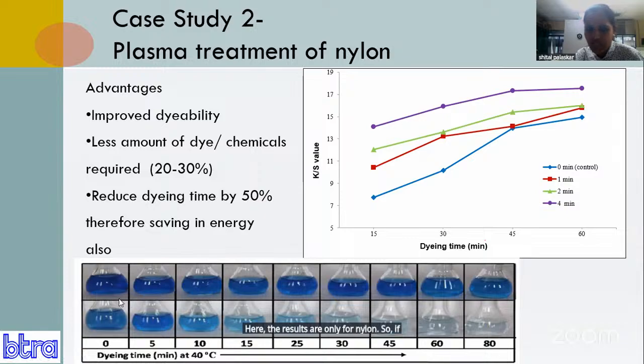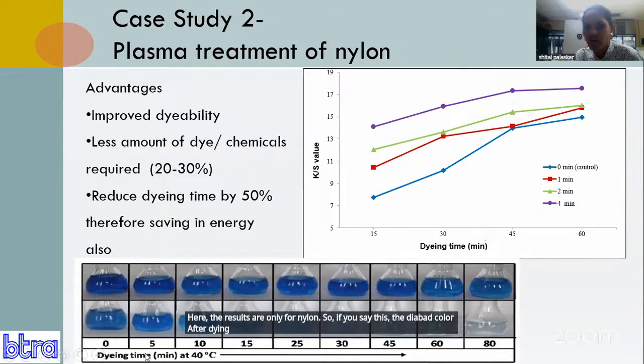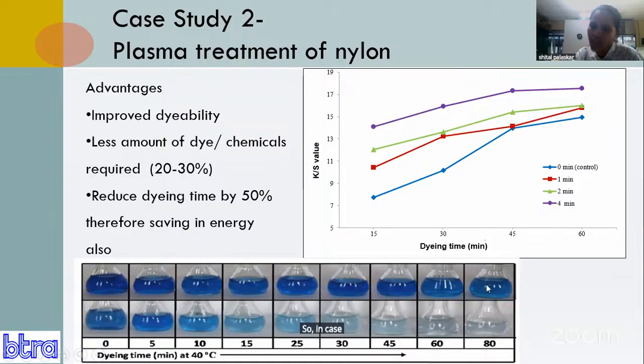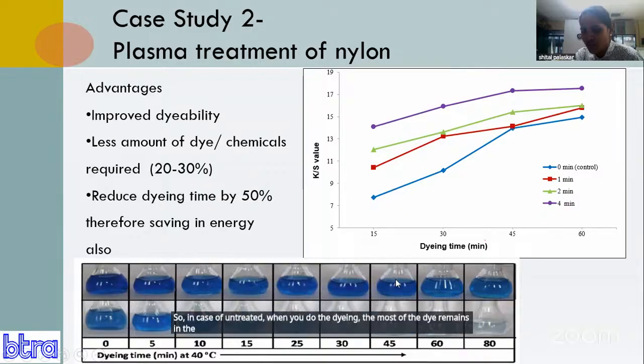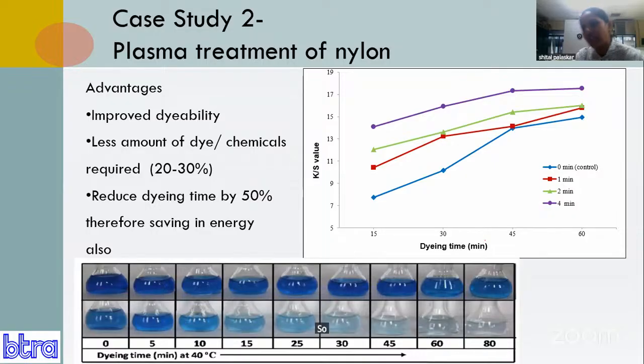If you see this, the dye bath color after dyeing at 40 degrees centigrade for various durations, the lower one represents the plasma treated and the upper one represents the untreated. In the case of untreated, when you do the dyeing, most of the dye remains in the dye solution itself, whereas after plasma treatment, the dye gets transferred onto the fabric and the solution becomes colorless. So in this case, we can say that after plasma treatment, the dye absorption increases.